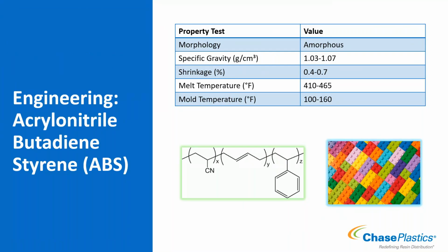So ABS is acrylonitrile butadiene styrene. Across the chemistry, that's what you see here. In this section is your acrylonitrile, your butadiene, and your styrene. So you'll notice the styrene, if we remember our chemistry and that these little joints here represent a carbon, this is actually the same then monomer and chemistry of your standard polystyrene. So ABS is made up with styrene being one part of the polymer.